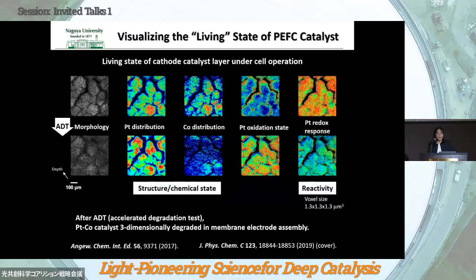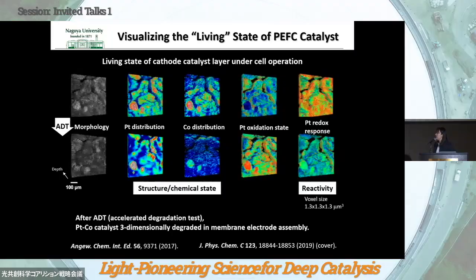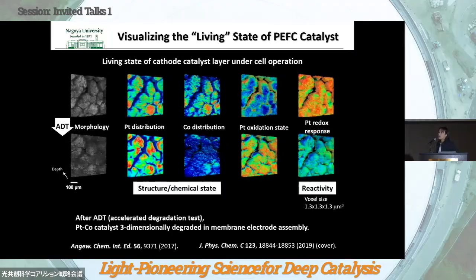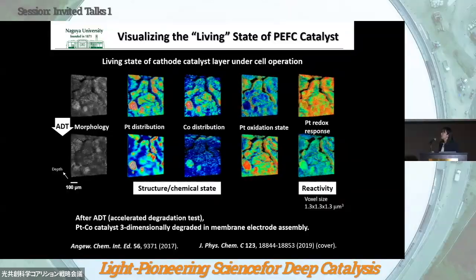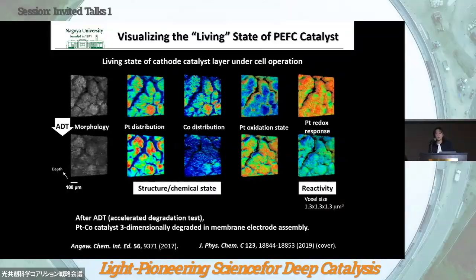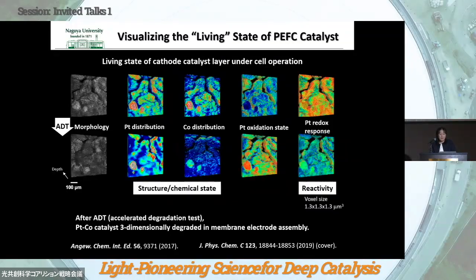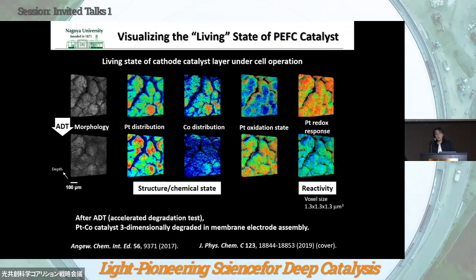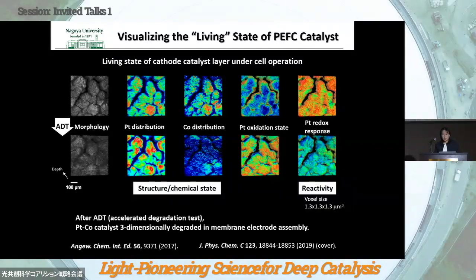So here I'd like to show you the first example, visualizing the living state of the PEFC catalyst under working conditions. We can reconstruct the morphology image, the platinum distribution and the cobalt distribution from the platinum L-edge and the cobalt K-edge XAFS spectroscopy. We can calculate the platinum oxidation state by calculating the white line height at the platinum L3-edge. We can also apply operando measurement by changing the cell voltage, which shows us the redox response of the platinum catalyst under the working conditions, which is strongly correlated to the reactivity of the catalyst.